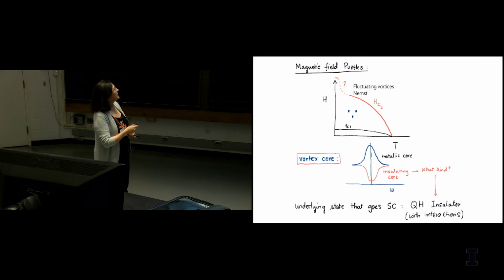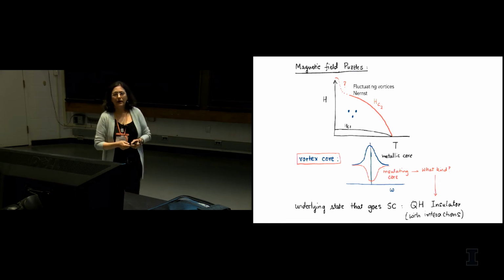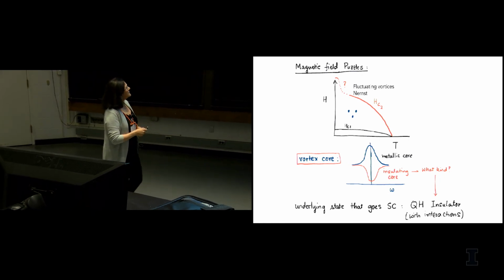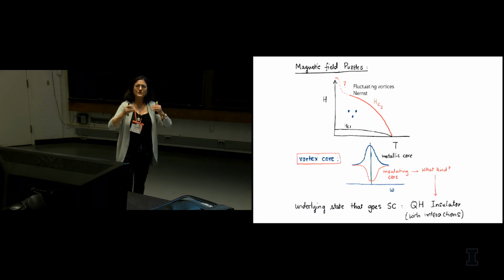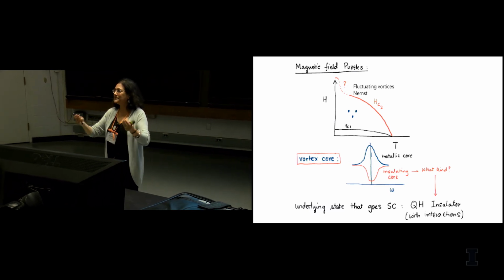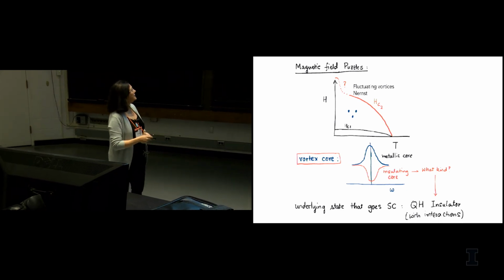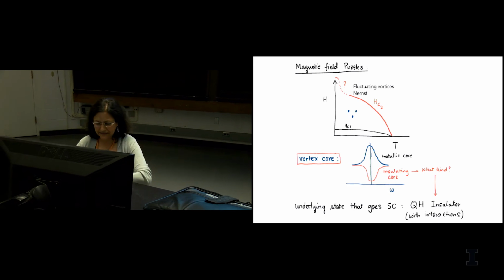But really, how does this behavior change as you go to extremely high fields? It's not clear that the usual BCS behavior of HC2 describes such systems, and there is growing evidence that the curve really goes up, and it's not even clear it's closing at any particular field as the temperature is lowered. The nature of the vortex is also quite mysterious. One would have expected that when you suppress superconductivity, you reveal the normal state, which is usually metallic. Instead, one is seeing insulating cores in some recent experiments.